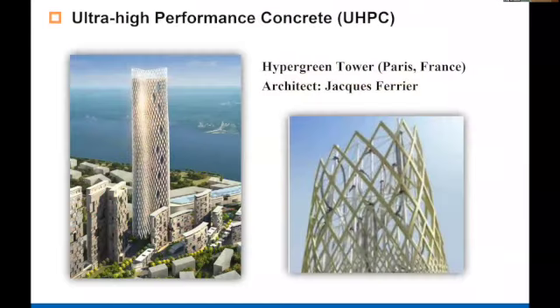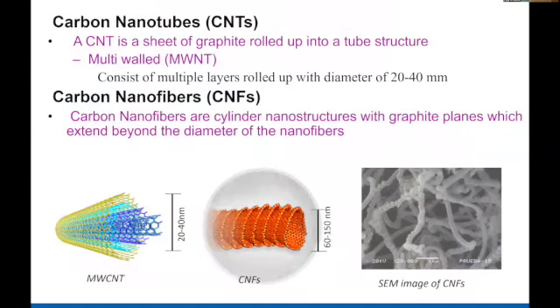For example, here are some buildings where the facade, this is in Paris, was designed in UHPC. So at this point, what I want you to pay attention to is that when you go from macro fiber to microfiber, you can get strain hardening cement-based composite. So then the next thought is, why not use nanofibers? Because cracks start at the nano scale. And many people have been working on using several nanofibers. And I suppose the most common one is carbon nanotube or carbon nanofibers.